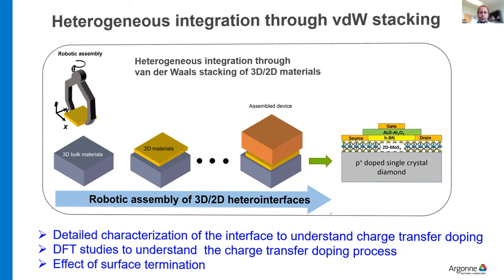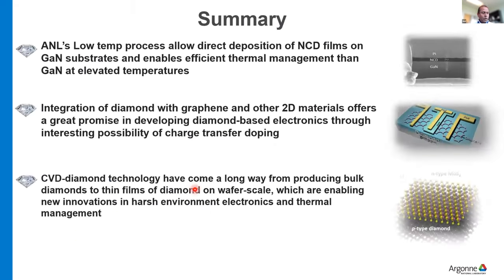So with that, I think I'm coming towards the end of my time, and I would like to summarize by saying that with this low temperature process, we have already shown that it's possible to integrate diamond with gallium nitride. And this approach could be used for GaN HEMTs, where you can deposit diamond near the junction to really get the benefit of thermal heat dissipation through the devices.